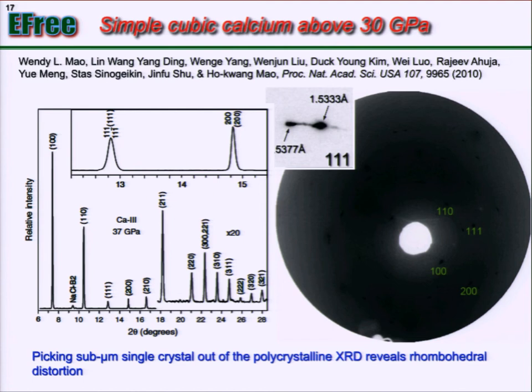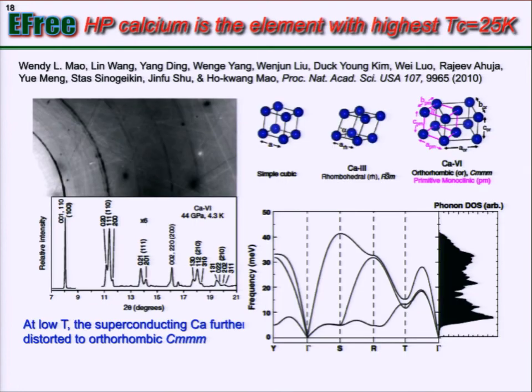And we don't have a large single crystal, so we used a very small crystal with a nano probe to determine the structure. Actually, it was not simple cubic. It turned out to be a rhombohedral distorted phase. It expands some, but not all that. But at higher pressure, it has even more transitions. So the simple cubic is just like this, and then the actual rhombohedral is like this. But at low temperature, it has another structure. It's an orthorhombic structure.